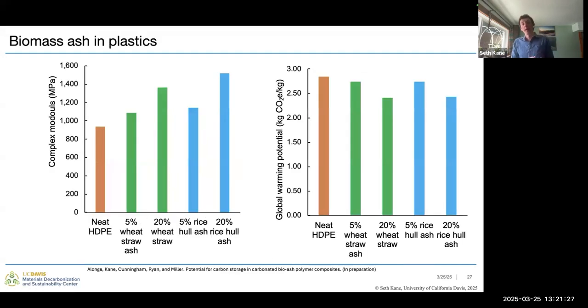We can do something similar by putting that biomass ash into plastic. So again, we've got a measure of mechanical properties on the left and our global warming potential on the right. And we're using, in this case, 5 and 20%. Again, both that wheat straw and that rice hull ash. And so we can see that we're going to increase the modulus of those plastics, so get a stiffer plastic out as a result of the inclusion of this ash. We would expect a little bit less of a chemical component to this. It's mostly just a filler in these materials, and that filler is not deforming as much as our plastic. So it makes sense that it would get a little bit stiffer.